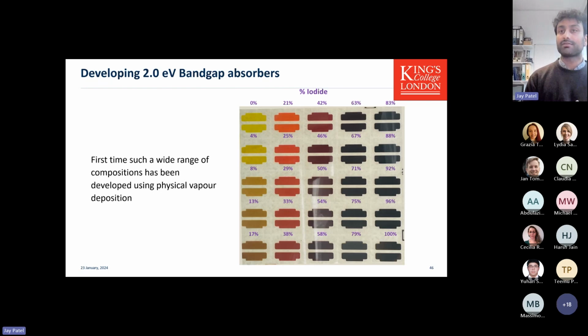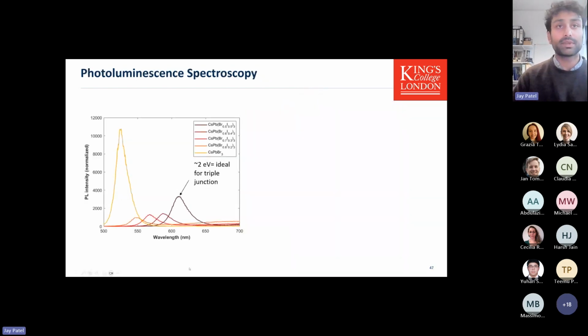But is this enough? I would like to make a material that absorbs all the blue photons. As you can see here, I did photoluminescence spectroscopy, where you shine light and light is emitted, and that emitted light is representative of the band gap. You can see over here that the photoluminescence spectra says I've developed a material which has 2 electron volts, which is ideal for the triple junction.